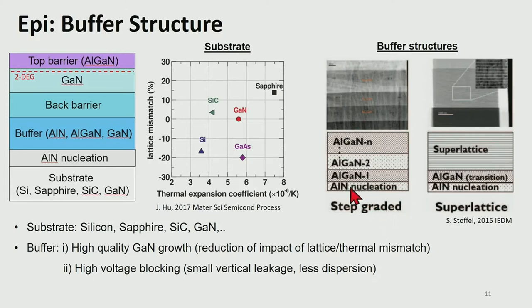On top of the aluminum nitride, we start with a higher aluminum percent AlGaN layer and gradually reduce the aluminum percent through multiple steps so that we can reach the gallium nitride. Another option is a superlattice, which alternates aluminum nitride and gallium nitride, or aluminum nitride and aluminum gallium nitride. Once the buffer growth is done, the next step is the back barrier.